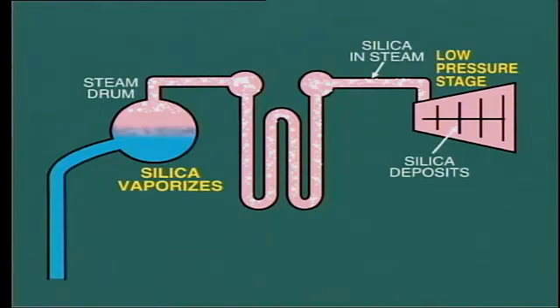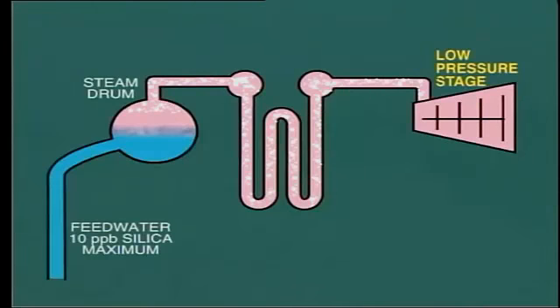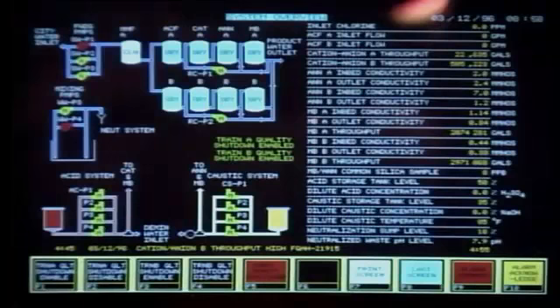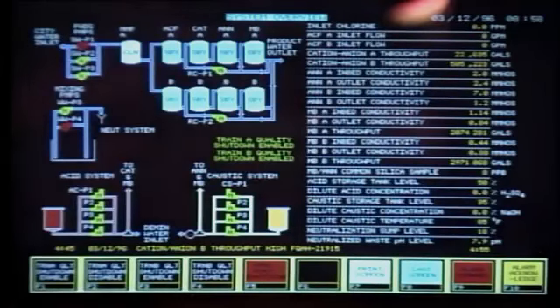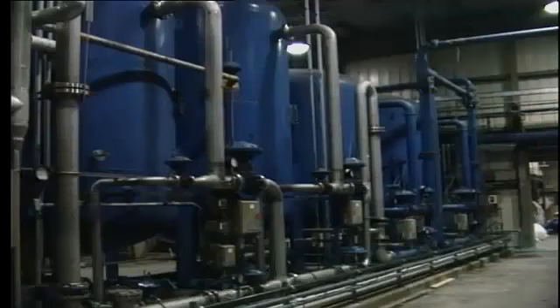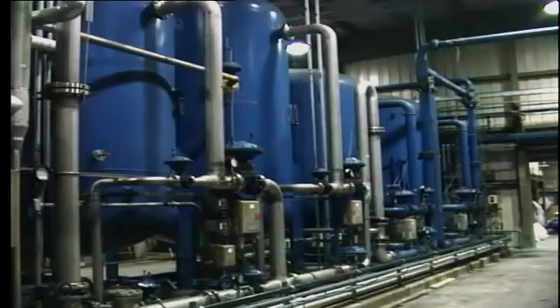But how can we reduce the silica content if it is higher than this? Well, one way of reducing silica content is to increase the continuous blowdown from the boiler drum. This is not a very efficient procedure because we are wasting heat and water, but it may be the only solution. If possible, a far better method is to eliminate or reduce to a very low level the amount of silica which enters the boiler with the feed water. In order to achieve this condition, we need particularly high quality water treatment equipment for producing makeup water. We shall be talking about demineralizers and other water treatment equipment in another module in this program. The problem of silica is so serious that in the event that we cannot reduce the silica content in boiler water, it will be necessary to reduce the operating pressure on the boiler, and consequently, the power output of the unit.